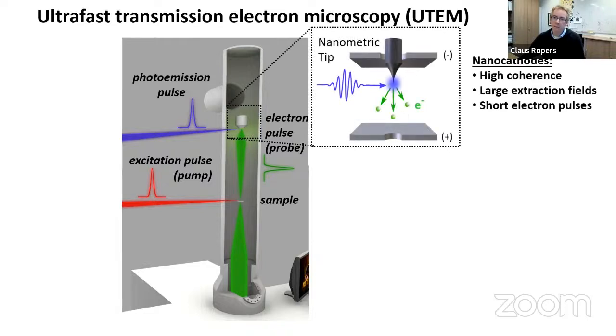And one of our primary areas of emphasis in the development in the last years has been to really work on the photoelectron cathode, which produces the pulses of electrons, and to make sure that we get the best temporal resolution and best spatial resolution from these electron pulses. Our approach has mostly been focusing on nanotip cathodes, so sharp needle cathodes, where the electrons are emitted from the very apex of these tips, because this ensures both high spatial coherence of the electron beam, which allows you to get good diffraction and spatial resolution, and also short pulse durations, because the electrons are accelerated up to fast velocities in the very close vicinity of the tip.